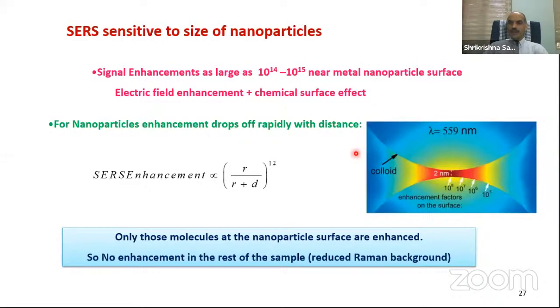The metal nanoparticle will be covered by this capping agent. And what does it mean? If you have the capping agent and then you put the probe molecule, what will happen? This probe molecule is away from the metal nanoparticle surface, and therefore the enhancement will be lower. So I have to have a metal nanoparticle without capping agent to get higher enhancement.